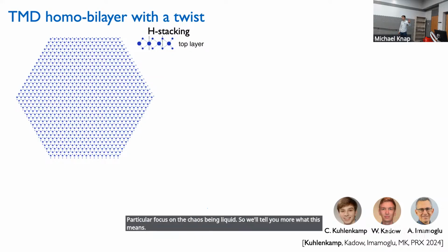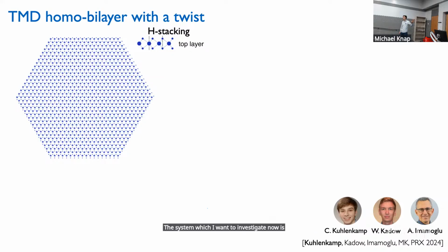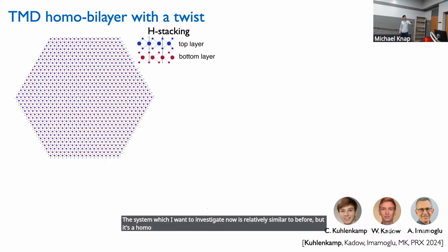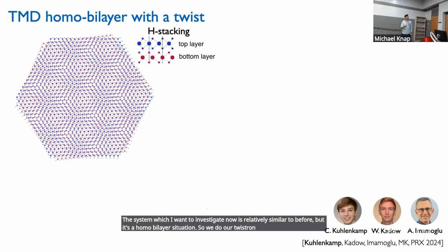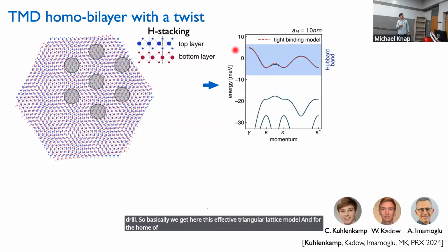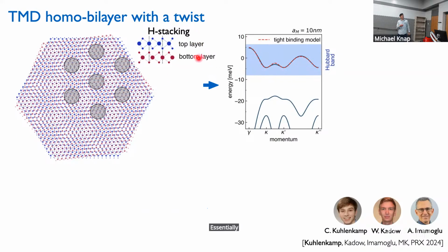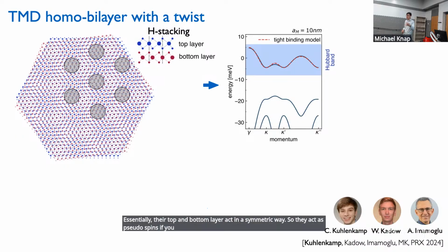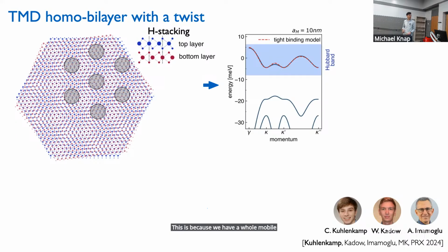The system which I want to investigate now is relatively similar to before, but it's a homobilayer situation. So we do our twistronics again, so you know the drill. Basically we get this effective triangular lattice model. And for the homobilayer, it turns out that we literally get a single Hubbard band, essentially, where top and bottom layer act in a symmetric way. So they act as pseudo spins, if you want, of the electrons. So there are two bands which are degenerate for the top and for the bottom layer. This is because we have a homobilayer TMD system.